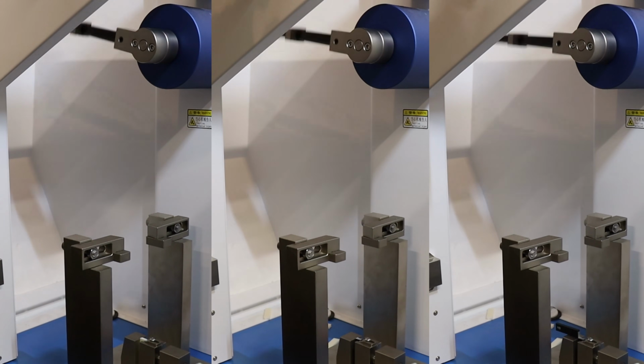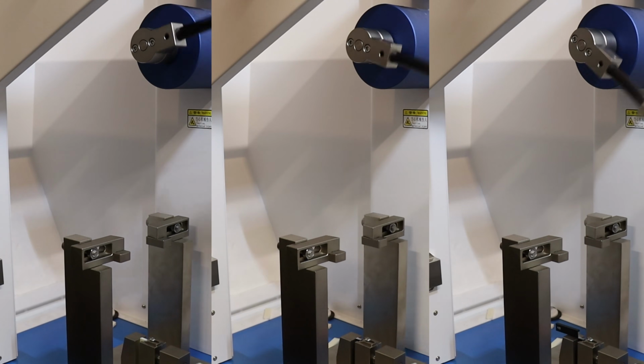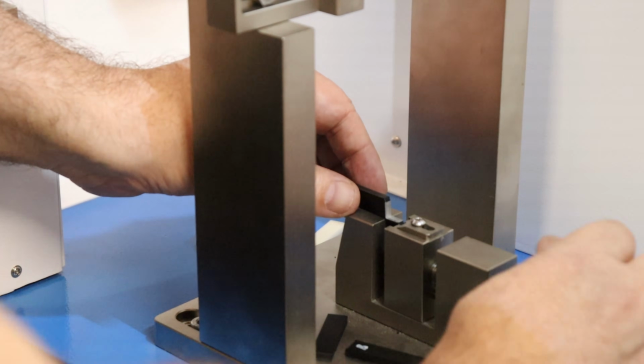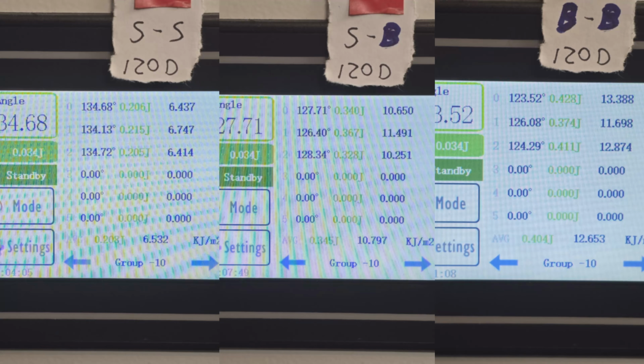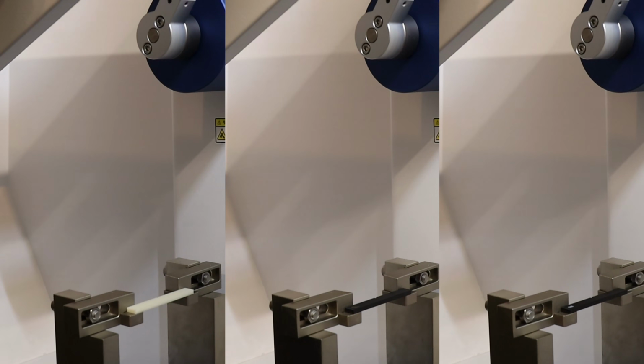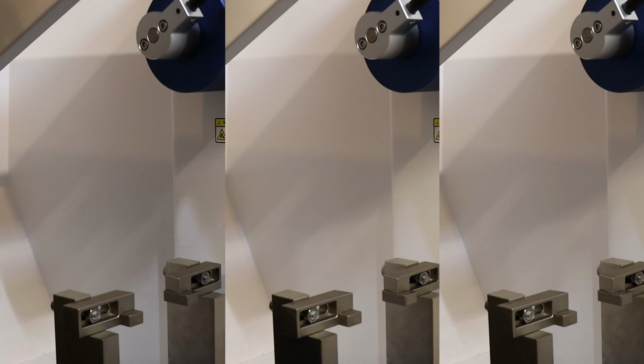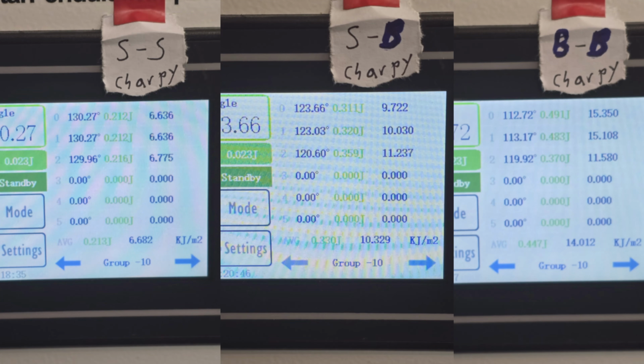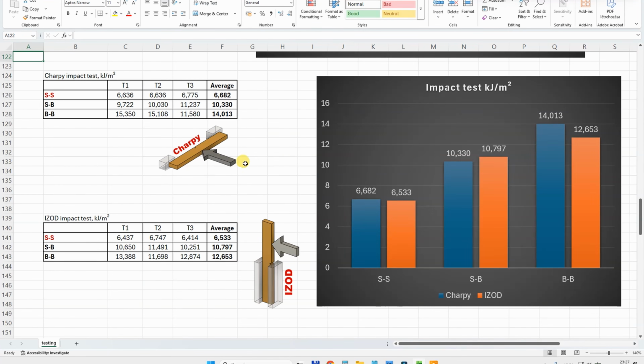Impact test. IZOD standard. No complete break with the Bambu test objects. All results a little bit chaotic, but don't worry, I will show you later everything in a table. Charpy standard. And again all 9 results. These two are different types of tests, so the numbers are not really comparable to each other, but always get very similar values. And we can see that in this case the Bambu Lab ABS is the toughest and the most brittle is M30. And the P430 is somewhere between.